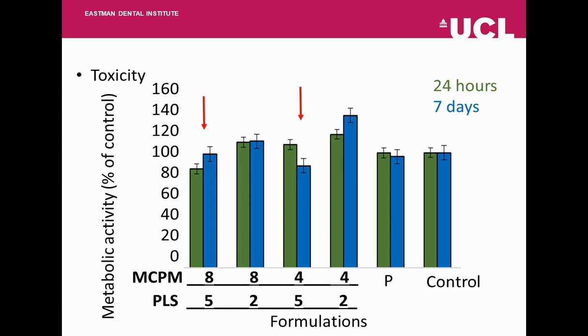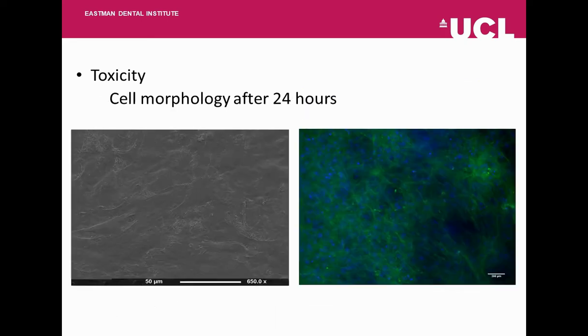And we can see that the cells that were exposed to the composites with higher levels of polylysine were lower than the composites with lower levels of polylysine. So we believe that too much polylysine isn't always good for the cells. And I'd like to add also, often polylysine is actually used to plate some materials, often to encourage cell attachment. At the same time, the study shows that maybe too much polylysine may not be great for the cells, but further analysis needs to be done on this.